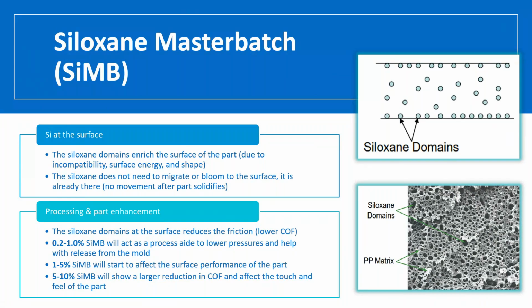So less than 1%, it's going to be a little bit more of just a processing aid. So we're going to lower our pressures a little bit, maybe release from the mold a little bit easier, and that's about it. Anywhere from 1 to 10% though, we're going to start to affect the actual surface performance of the material. So we're looking at low COF, affecting the touch and feel of it. You do keep in mind different grades might also utilize different molecular weight silicone in them, which then might also dictate the amount you should be using. And so with any additive, always check the recommended usage and percentage and follow that for what you're trying to achieve.